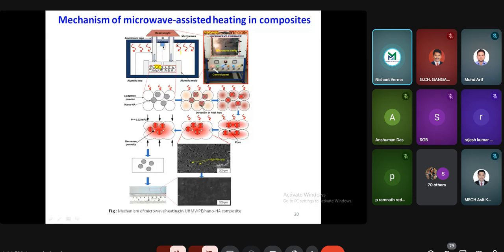Whenever the microwave comes, what happens? It directly interacts with the nanohydroxyapatite, and it also interacts with the ultra high molecular weight polyethylene powder. But it interacts more with the nanohydroxyapatite. Why? Because the dielectric constant value of nanohydroxyapatite is greater compared to the ultra high molecular weight polyethylene. So firstly these particles heat up and transfer their heat to the surrounding material, and with the application of 0.02 megapascal load, this load we have optimized by trial and error. This load was sufficient to decrease the porosity.